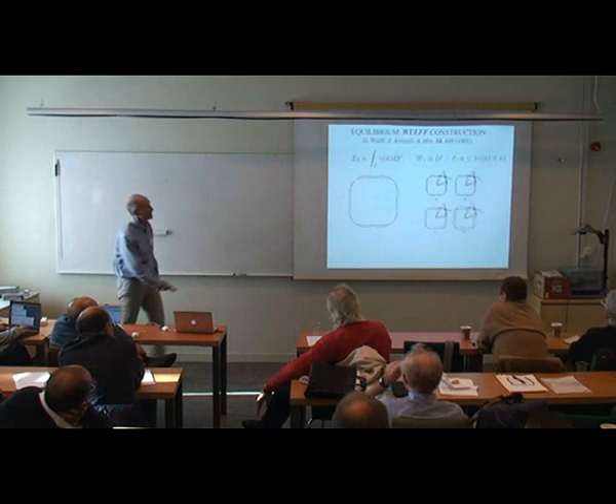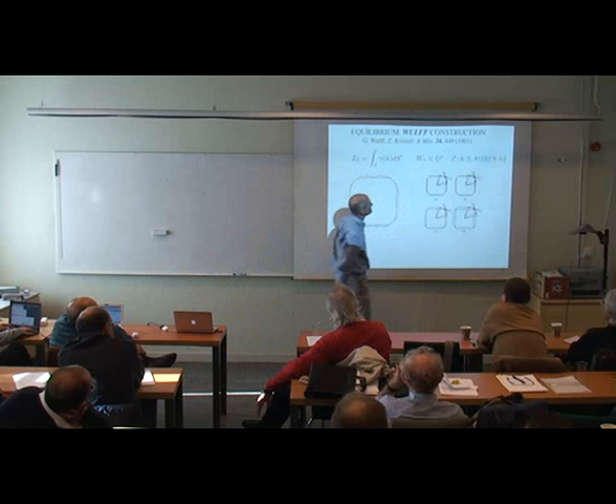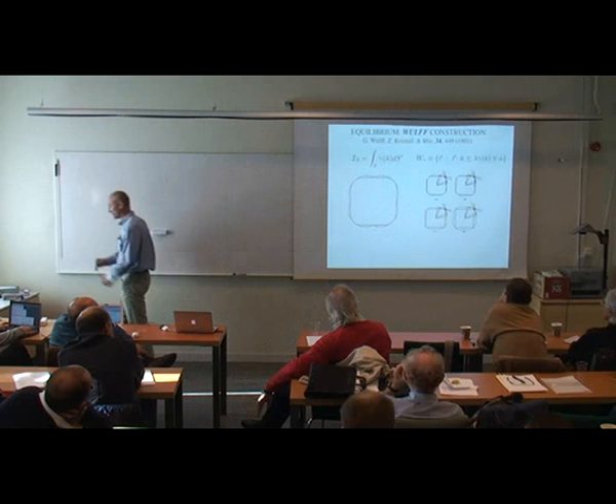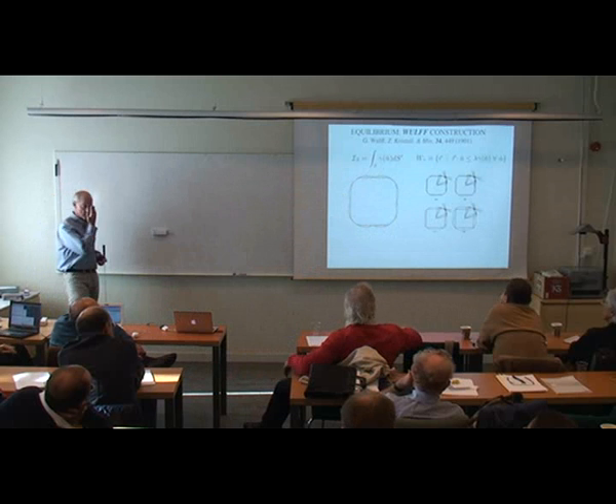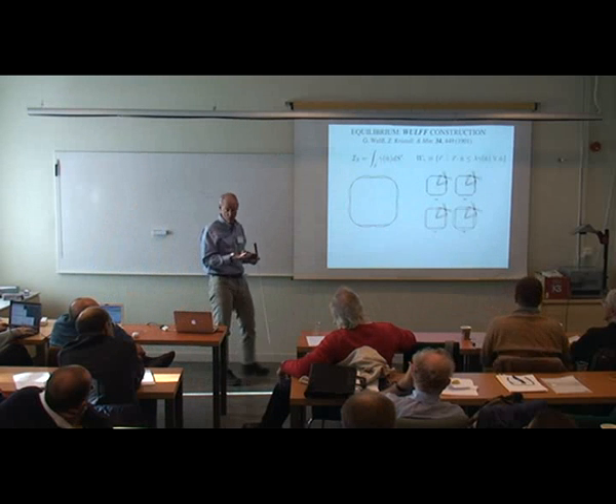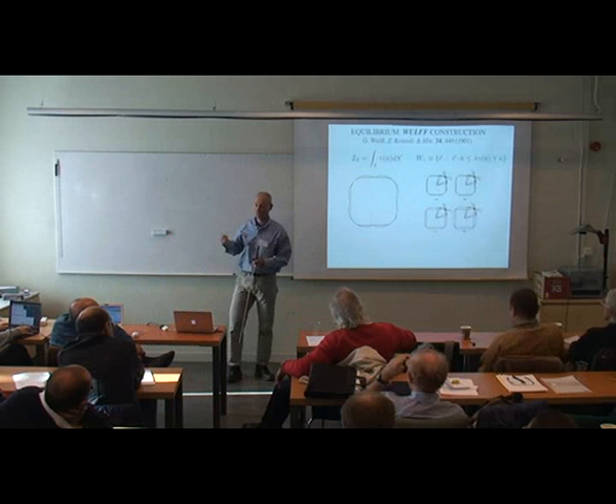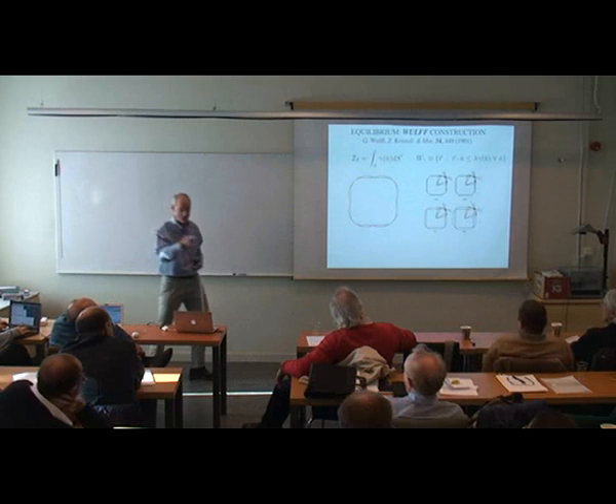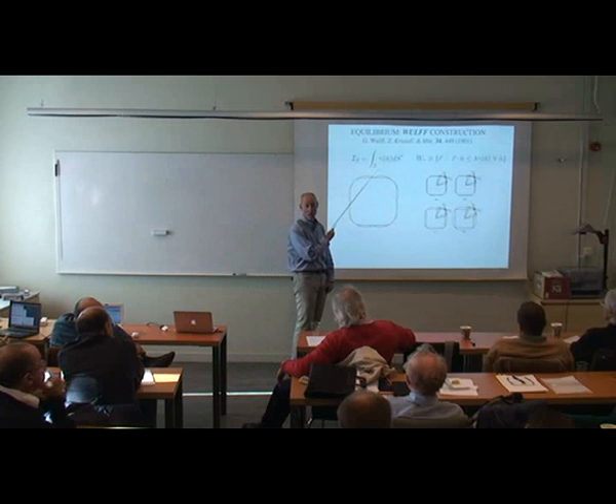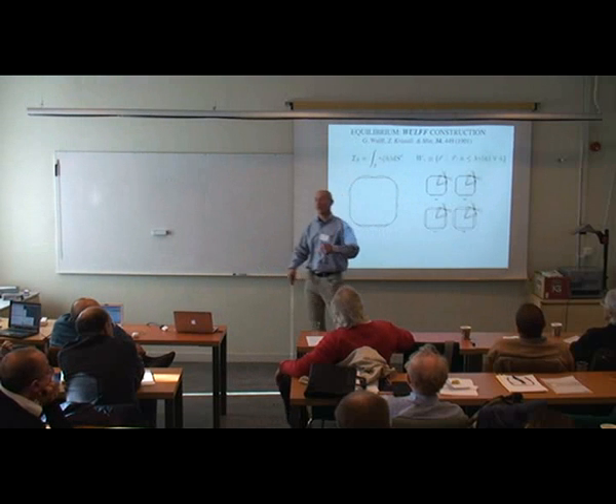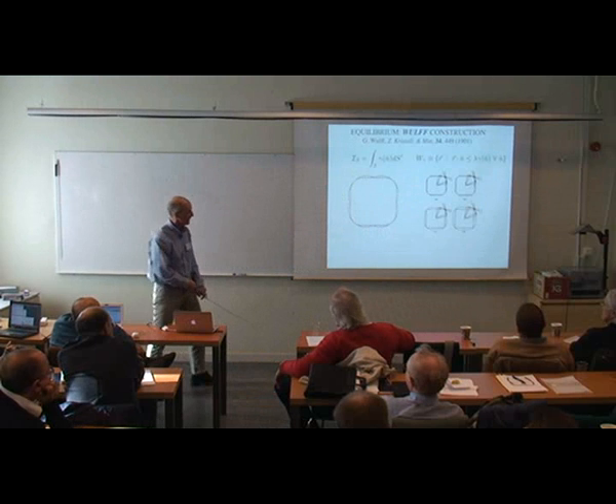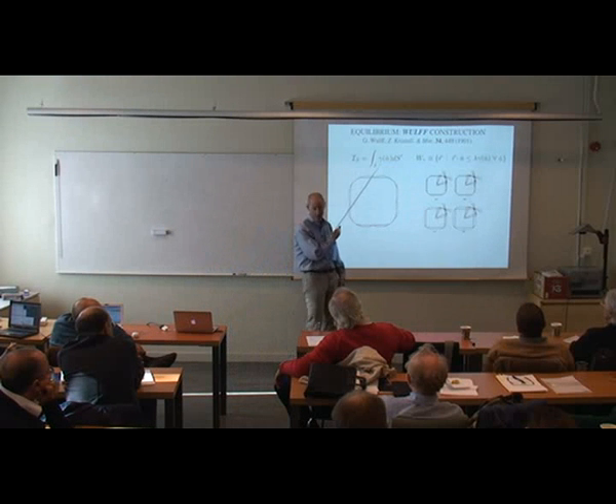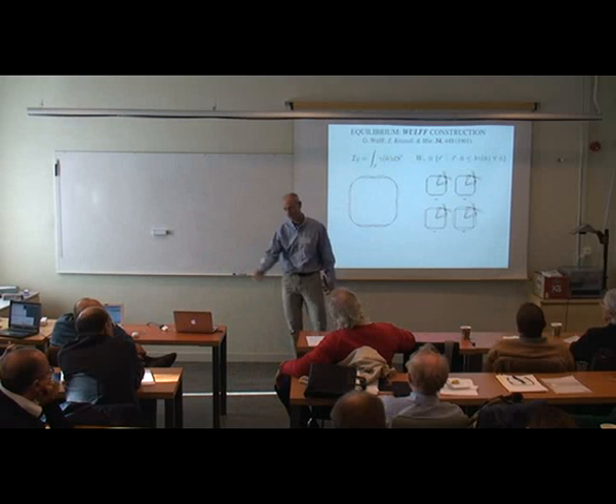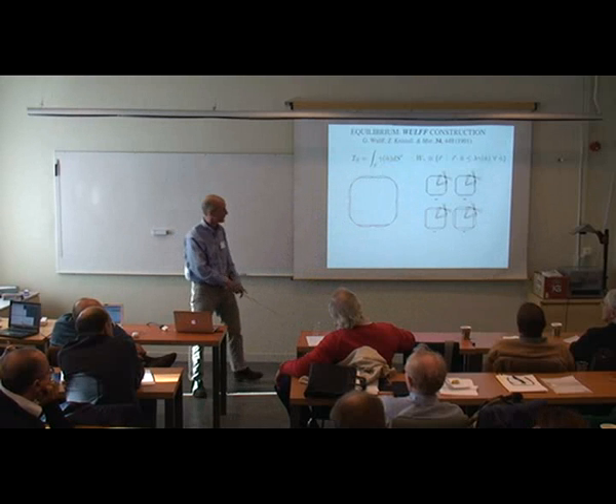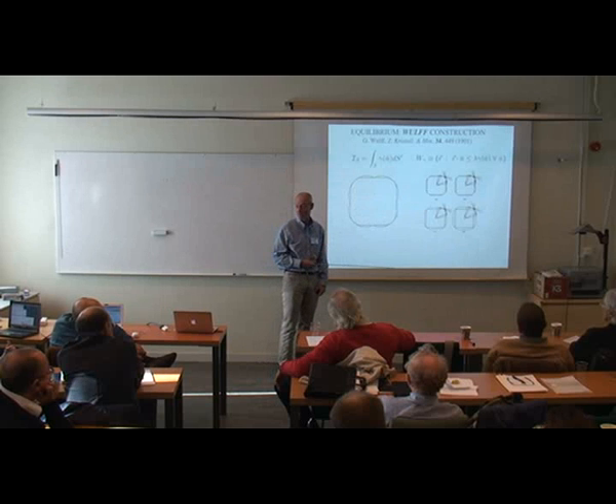In 1901, Wulff first described the notion, which I'm interpreting now in a slightly different way, that an equilibrium crystal shape is something that minimizes the total surface energy for a fixed volume. The Lagrange parameter is a fixed volume, so it minimizes this integral. But it proceeds in the following way. If God, or some close associate, walks up to you in the street and says, okay, lead, I'll give you the surface energy as a function of all possible orientations, here it is, then you just have to minimize this integral and you give me the shape. But God is never that friendly.